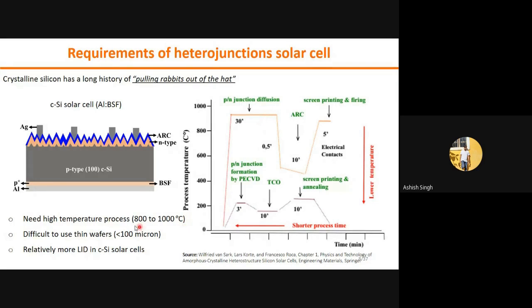Since it requires high temperature, if we use thinner wafers, less than 100 micron, bowing effects start coming. The wafer will start bending due to stress in the process, and reliability will be a problem. In addition to these points, some of the industry reported light-induced degradation in P-type crystalline silicon solar cell. Basically, this problem happens because of the boron diffusion.